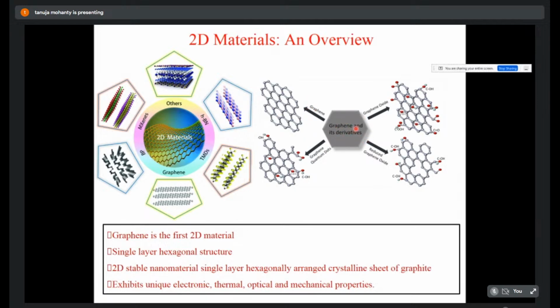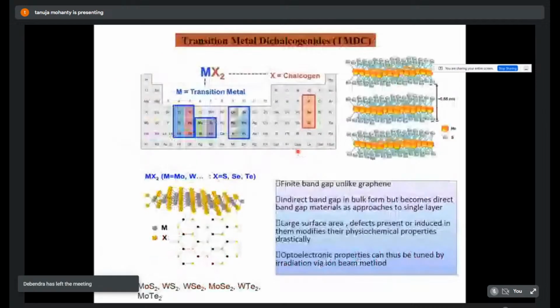And what is graphene and its derivative, graphene oxide? Graphene itself, and oxygen means you have the oxygen groups here, and graphene quantum dots can be present, meaning it is a graphene but having a zero-dimensional layer. And there is reduced graphene oxide, where some of the oxygens present in the graphene oxide get reduced. So why is it so important? Because of the very high charge carrier concentration as compared to its bulk. That is the first thing, and the other properties are because of the quantum confinement.